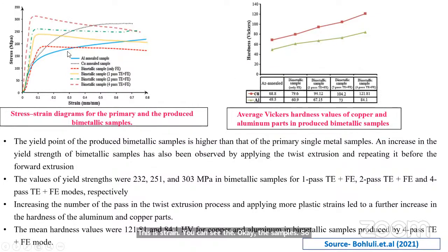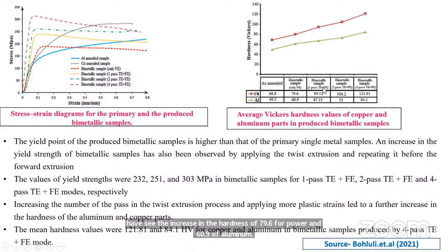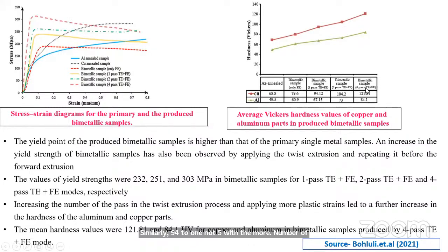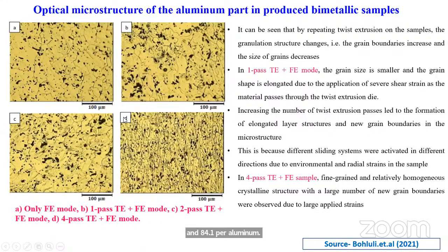A similar trend to what we noticed here is obtained separately. You can see the copper and aluminum. As annealed copper and aluminum, they took the hardness separately for aluminum and copper. Then after the bimetallic strip is produced, they compared this. As annealed, copper has a hardness of 68.8 and aluminum 49.5. The bimetallic sample with only forward extrusion showed an increase in hardness to 79.6 for copper and 60.9 for aluminum. Then with one pass twist extrusion plus forward extrusion, the hardness increased from 79 to 94. Similarly, 94 to 104.2 with more passes, and to 121.81 for 4 passes for copper and 84.1 for aluminum. So these are the microstructures. You can see the microstructure.